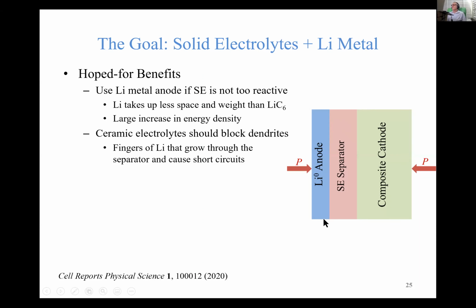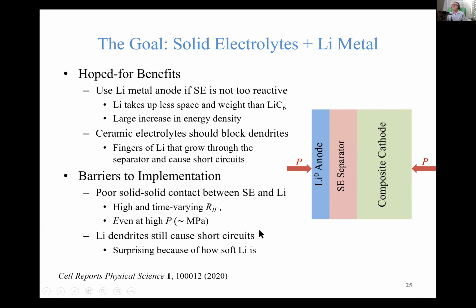And then there's other things that we could hope for. For example, since the solid electrolytes tend to be ceramic, or at least quite hard, certainly compared to lithium metal, we should expect that dendrites should be blocked. These dendrites are really fingers of lithium that can grow through a conventional separator and cause short circuits and fire. So we should hope that that doesn't happen.